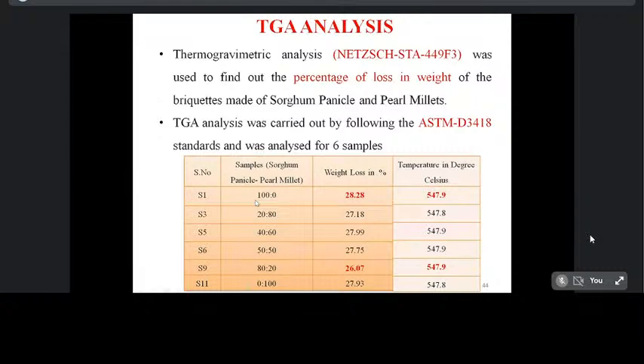Here the sample S1 has the highest weight loss, that is 28.28%, and its burning temperature is 547.9 degrees Celsius. The sample S9 has 26.07%, the lowest weight loss percentage, with its mixed ratio of 80% sorghum panicle and 20% pearl millet, and its burning temperature is 547.9 degrees Celsius.